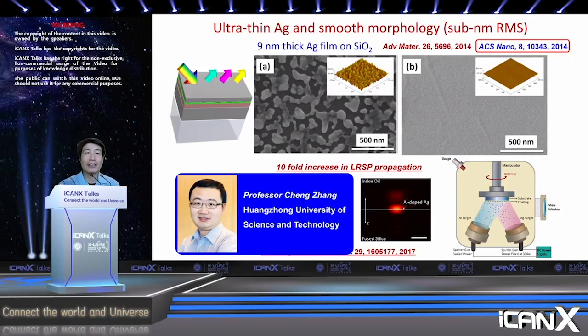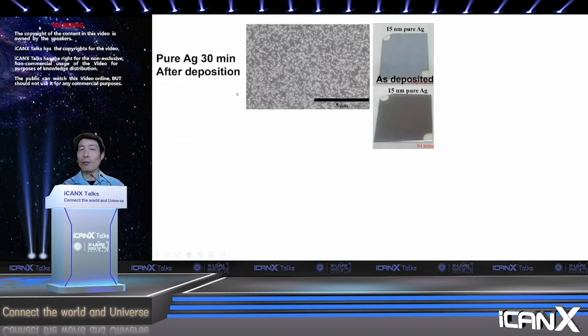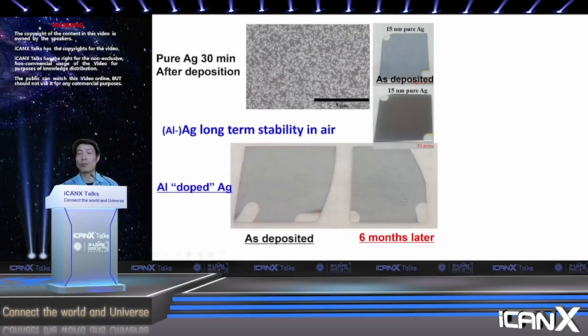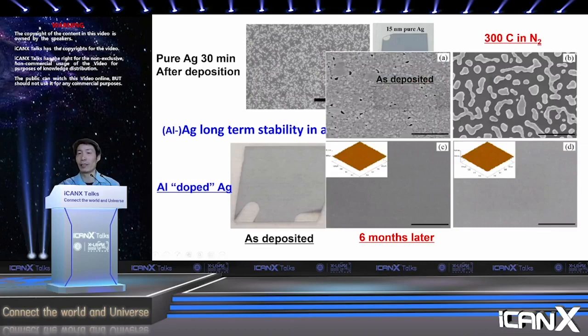So here you can see that another problem with pure silver is that after deposition, you take it out of the vacuum chamber, and in like 15, 30 minutes, you can visually see it becoming dark. It degrades that fast. But our film with a small amount of aluminum, after 6 months, at least in Michigan weather, we don't see any noticeable change. It's much more stable. Now, a silver film, if you make it thick enough, is continuous. But if you heat it to, for example, 300 degrees, it will dewet, almost like water droplets. But this film, no problem. It can stand this temperature as long as you do it in nitrogen, to prevent oxidation. So it's much more stable.